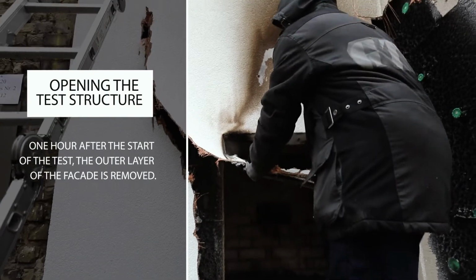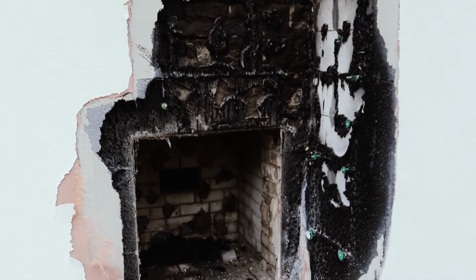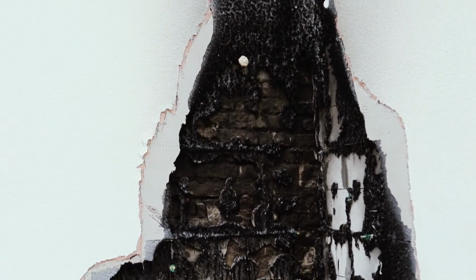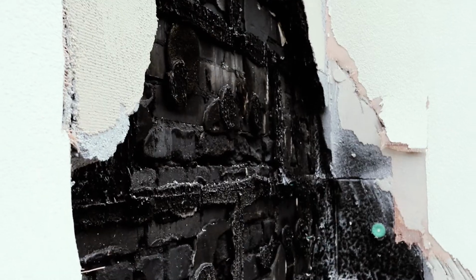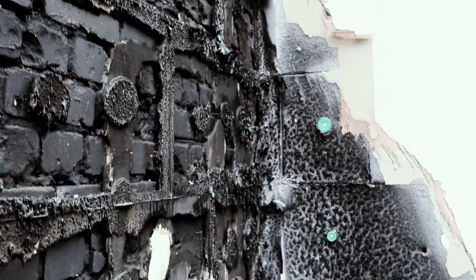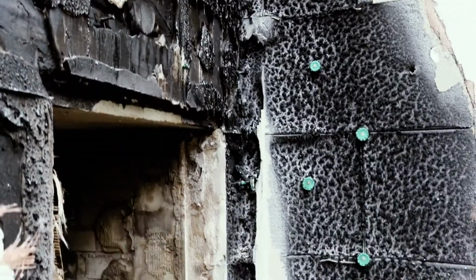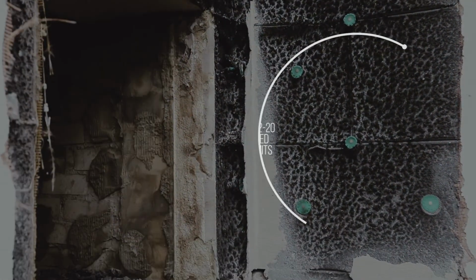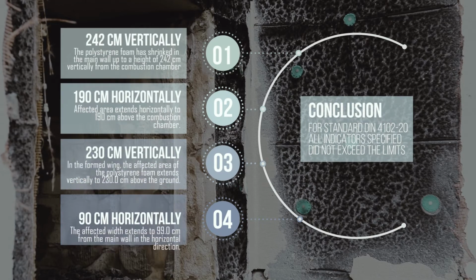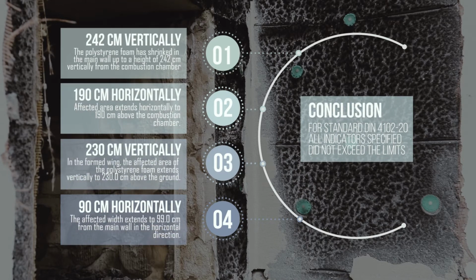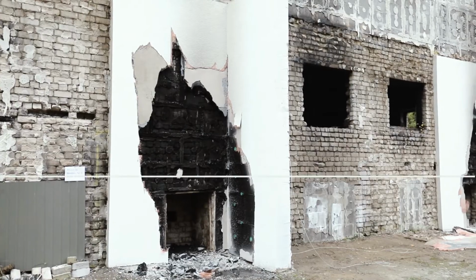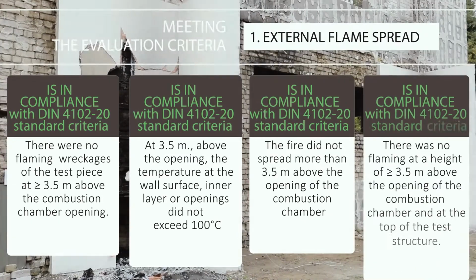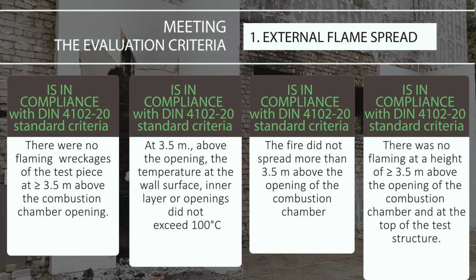When the outer layer of the test structure is removed, it is found that the polystyrene foam has shrunk in the main wall up to a height of 242 centimeters vertically from the edges of the combustion chamber, while horizontally the affected area extends to 190 centimeters above the combustion chamber. The affected area in the formed wing extends vertically to 230 centimeters from the ground and horizontally to 90 centimeters from the main wall.